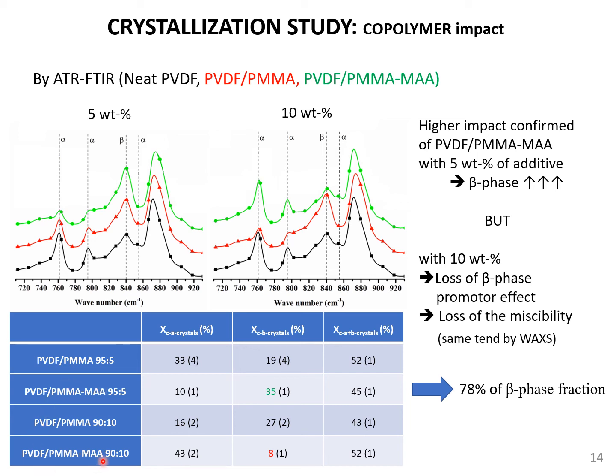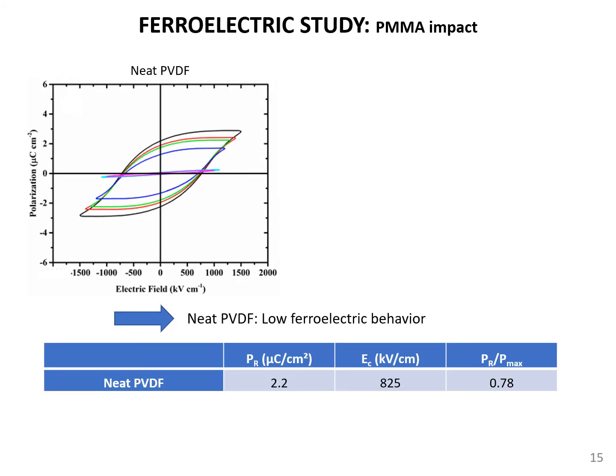However, this effect is less pronounced at 10%, and you can also observe a reduction of the beta phase content. This is more related to the fact the copolymer may be less miscible with the PVDF by comparison with the PMMA. So after investigating the crystallization behavior, we wanted to know about the ferroelectrical behavior of this blend.